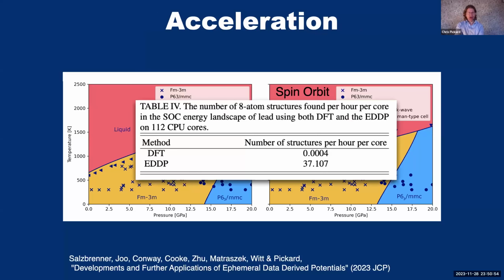So this is one of my favorite tables that Pascal has produced, which shows us just how much faster for searching his new potential was compared to DFT. In his table, he has two entries, DFT and EDDP, and his quantity is number of structures per hour per core. For DFT, it was 0.0004 structures per hour per core. And for EDDPs, it was 37. Now, this is a factor of about 100,000 different, which is completely transformative.